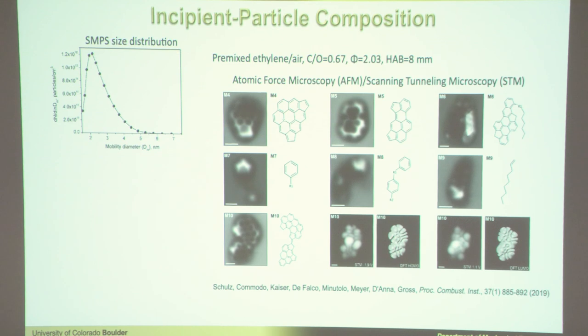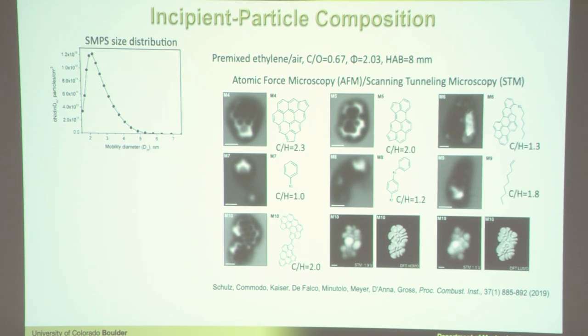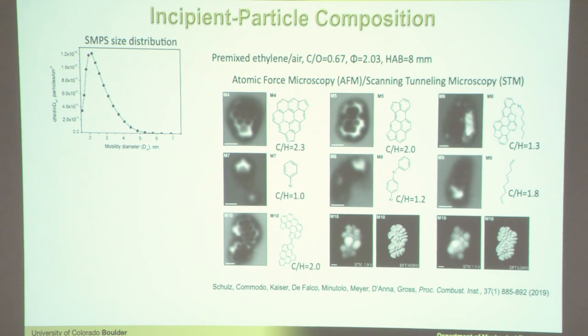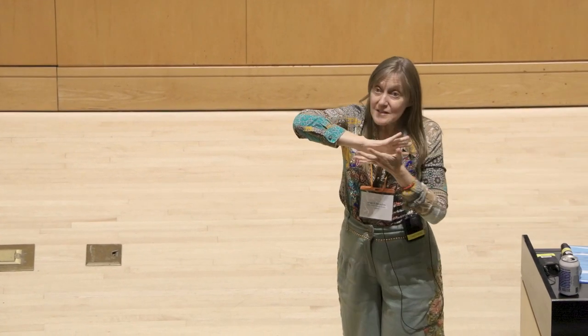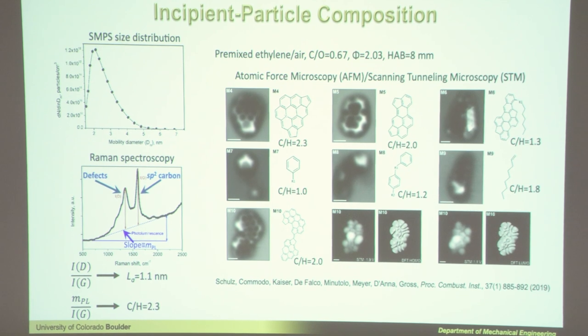This experiment backs up work people were doing just before — ideas that five-membered rings should be important and radicals should be important. Below each of those species I've added their carbon-to-hydrogen ratio. Remember: when people extract from the flame and do elemental analysis, they see a C/H ratio of about 1.3 to 2. Here are some of the C/H ratios of species just observed and imaged in that experiment — they're right in that range. So it does look like these species may be part of the particles.